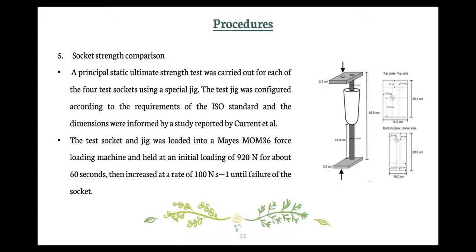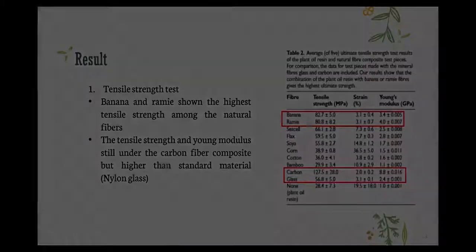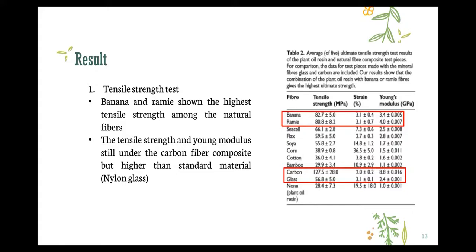And then the socket strength comparison test was performed, and they put the socket into the jig test, and then the socket and jig were loaded into the Mayes MOM36. The force loading machine held initially a loading at 920 Newton for about 60 seconds, and then increased at the rate of 100 Newtons per second until it reached the break point.